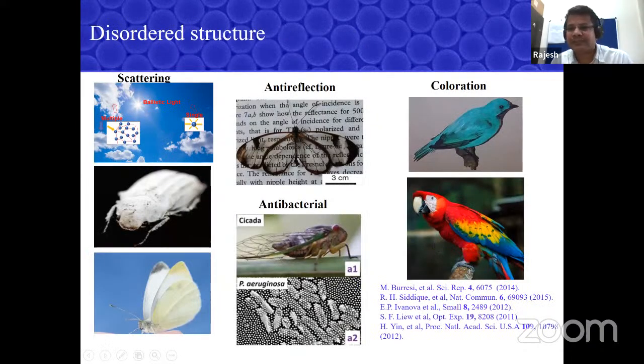Before doing that, disordered photonics is everywhere around us, even in the blue color of the sky. You can have ballistic, single scattering, multiple scattering. You have these nice white butterflies. They look white because it's a multiple scattering system. And there are many creatures which have a very disordered structure in their wing scales, and that gives them anti-reflection properties or antibacterial properties, which help their survival. And some of these birds have nice colorations also due to this kind of disorder, but with a correlated, connected disorder. In very layman language, the disorder is quite connected.